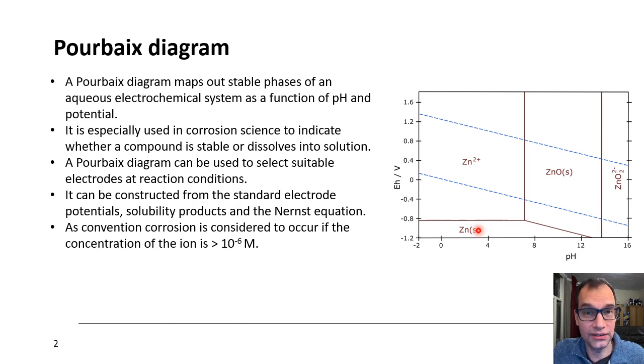Zinc is quite a non-noble metal, so you really need to go to low potentials to enable a stable phase for metallic zinc. So that is also shown by this Pourbaix diagram, but it shows much more. It also shows that at higher pHs you get oxide formation. So there's quite some information you can get from a Pourbaix diagram. It's often used in corrosion science, where it basically helps determine whether a material corrodes or not.